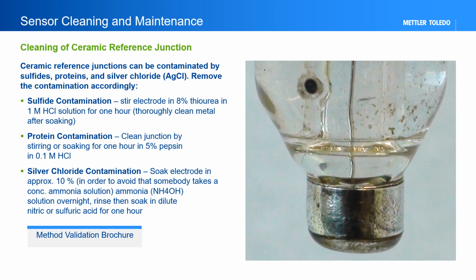Sulfide contamination can be removed by stirring or soaking for 1 hour in a solution of 8% thiourea and 1 molar hydrochloric acid. Protein contamination can be removed by stirring or soaking the electrode for 1 hour in a 5% pepsin and 0.1 molar hydrochloric acid solution. Silver chloride contamination can be removed with an overnight, approximately 8 hours or more, soaking in 10% ammonia. This must be followed with a thorough rinse and soak in a dilute acid.